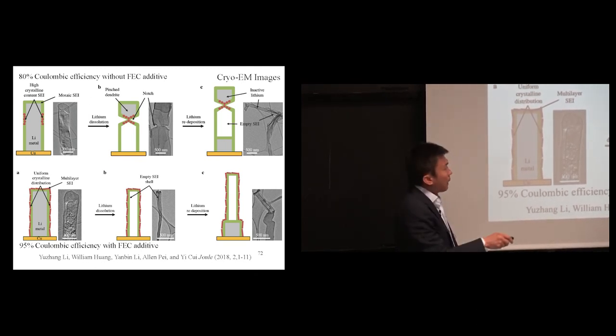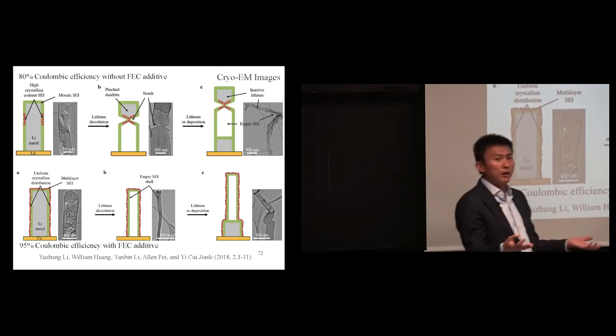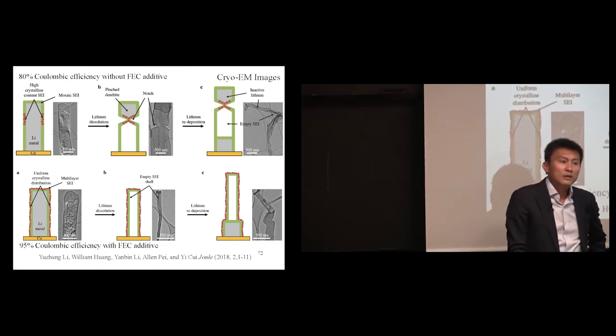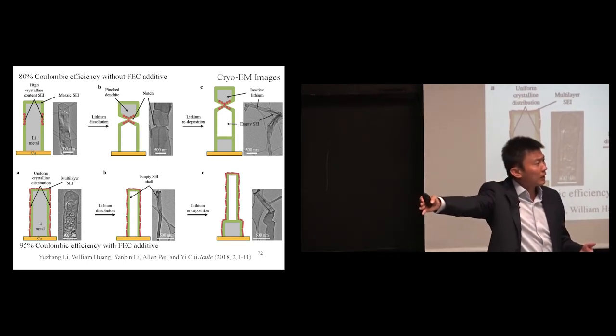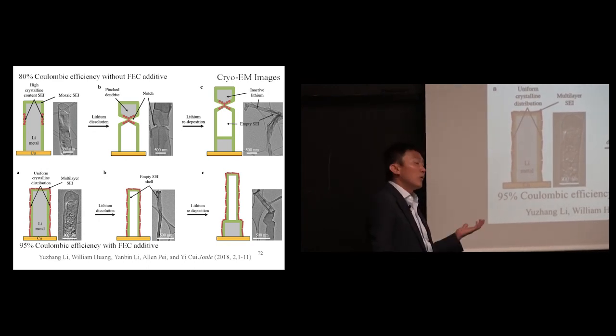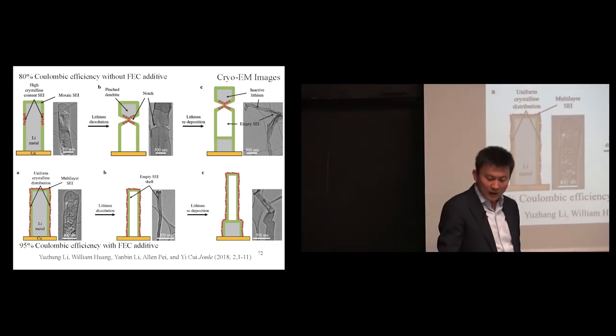And then electrochemistry-wise, we notice a huge difference in its performance. With the EC-DEC alone, you only have 80% coulombic efficiency. You charge 100 electrons, you only get 80 out. And then once we look at this, we do lithium stripping halfway. Now we see this notch formation. And we zoom in a notch, we find out this inorganic particle concentration is very high. Apparently, having this high concentration of inorganic particle right there, lithium ion conductivity is much higher. When you do stripping, this is the place stripped really fast. And then this cause the pinch off. If you pinch off, the bottom gets stripped away, and the top will be disconnected from the current collector, you have dead lithium formation. That's why you lose so much lithium. And then for the uniform one, multilayer SEI, you see uniform stripping becomes thinner. So coulombic efficiency is 95%. You only lose 5% of that. Now cryo-EM is teaching us this can make a huge difference. Unfortunately, for both either of cases, the second time you deposit lithium, this lithium metal does not like to go into this initial empty shell. It will push out this empty shell and deposit underneath. So that's why lithium metal coulombic efficient, first cycle, second cycle, you just never get to 99%. You just keep, every cycle need to reform the SEI, consume too much lithium. I call lithium as a very expensive kid. Every home, every time, every night, lithium come home and tell daddy and mommy, I want a different house to stay in. That's what lithium is doing.